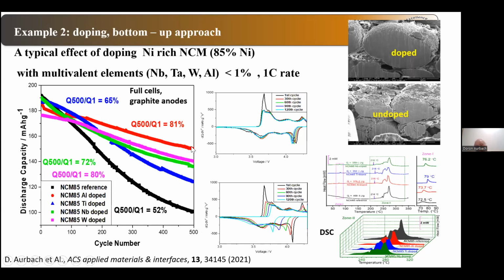The stabilization is well reflected by differential capacity curves. We see the stability of the voltage profiles. This is a derivative presentation of the voltage profiles during 120 cycles, and we see the stability of the voltage profile compared to the reference. And whenever we have electrochemical stability, we also check the thermal stability. We measure thermal stability by differential scanning